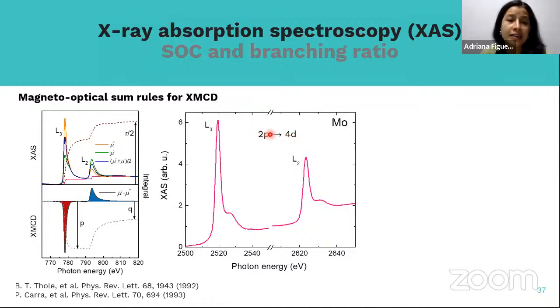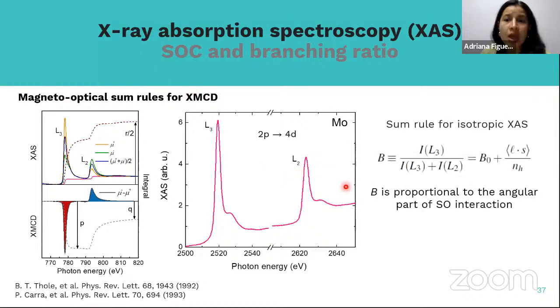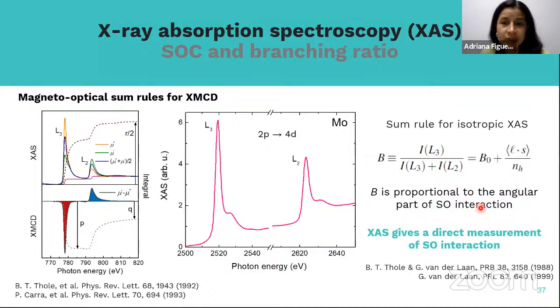This is because there is a rule, a sum rule, that has been established for this XAS, for this X-ray absorption spectroscopy, that correlates the spin-orbit coupling in the material with the intensity that we observe in this X-ray absorption. So the sum rule for isotropic XAS tells us that this branching ratio, which we define as the ratio between the intensity of these two transitions, the L2 and the L3, is proportional to the angular part of the spin-orbit interaction. So if we measure this on these materials, XAS gives a direct measurement of the spin-orbit interaction. So that's what we did.